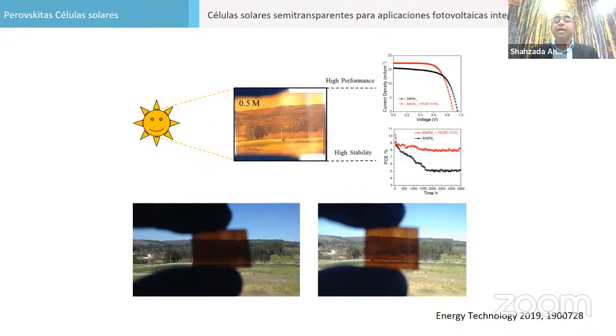BIPV with semi-transparent solar cells is also very important. If you decrease the thickness of the perovskite to 100 nanometers instead of going for high efficiency, and put some polymer matrix to bind it, we can achieve almost transparent perovskite solar cells, and it shows an efficiency of 11% to 12%.